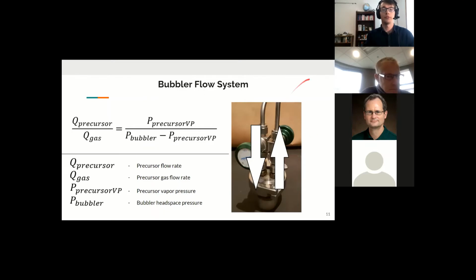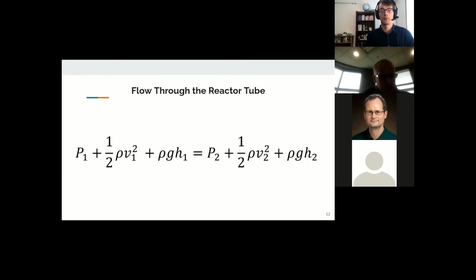So once the precursor gas leaves the bubbler, it joins up with a carrier gas. The carrier gas enables an operator to control the plasma characteristics without requiring the full flow of gas to be directed through the liquid precursor. In our system, we use the same mixture of gas for carrier gas as for the precursor gas. Another gas used in the system is the reaction gas, which mediates the precursor in the plasma. In the system, and as was alluded to before, hydrogen is used as a reaction gas to control the amount of excess carbon in the final formed nanocrystals. So the vapor saturated precursor gas, the carrier gas, and the reaction gas all meet upstream of the reactor and are introduced into the plasma mixed together.